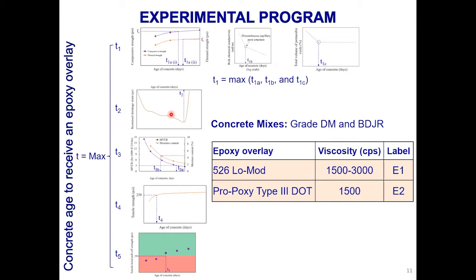And then we need to look at the cracking age of concrete, because if concrete is not cracked, it's going to crack at one point. So we want to apply overlay after concrete cracks. Someone can say if we apply overlays, it may prevent cracking. That's not the case. We can show evidence, and we'll have evidence in a couple later slides.